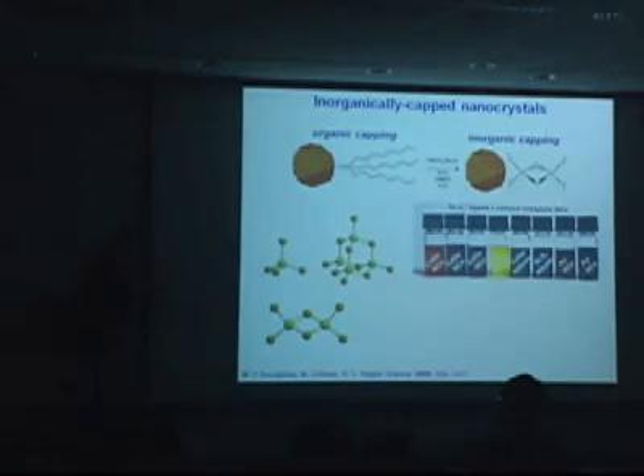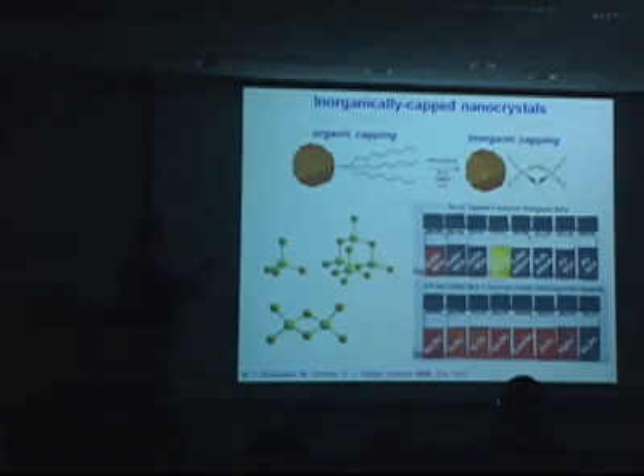So we have inorganic core, inorganic ligands, and it's a very general chemistry. For example, we can make this tin sulfide metal chalcogenide complex and use it with cadmium selenide nanocrystals, cadmium telluride nanocrystals, nanorods, cadmium sulfide nanorods, cadmium selenide nanowires, gold nanoparticles, and many other things. You can also do a lot of rational work on design of these ions. For example, you can start with cadmium selenide nanoparticles and use designed inorganic ligands based on tin, indium, gallium, copper, zinc, mercury, antimony, with sulfides, selenides, tellurides, and with different structures, different motifs. It's a very useful, very general methodology.